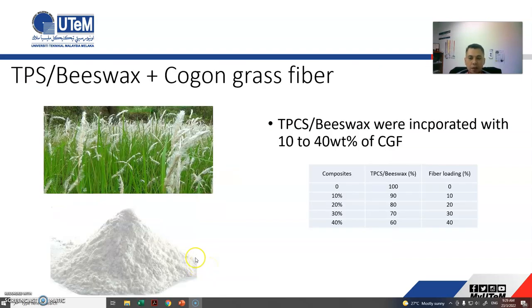For this study, we are not using the pure thermoplastic starch as the polymer matrix, but we are using the polymer matrix blend with Beeswax as the base material for this composite. Then we mix it with the Cogon grass fiber to investigate the performance of the Cogon grass fiber when it's mixed with these bio-based materials. We raise the loading from 0 to 40%.